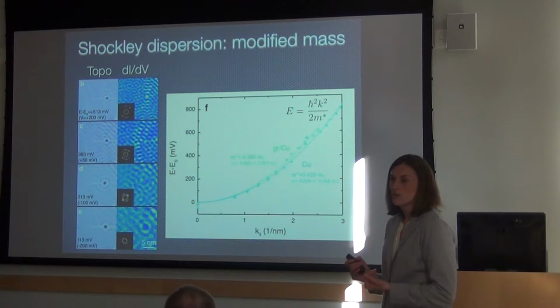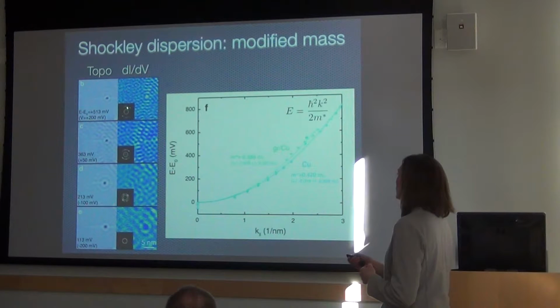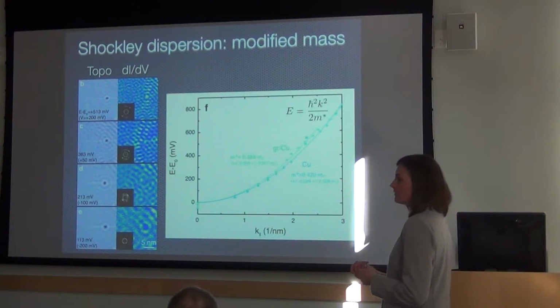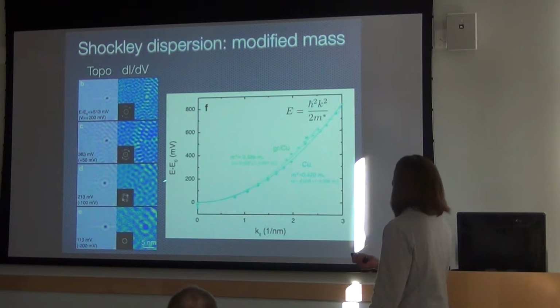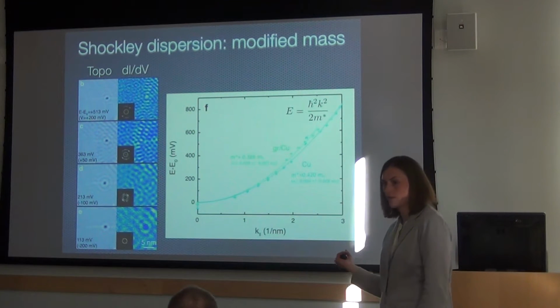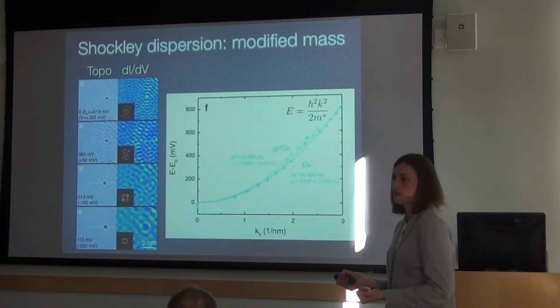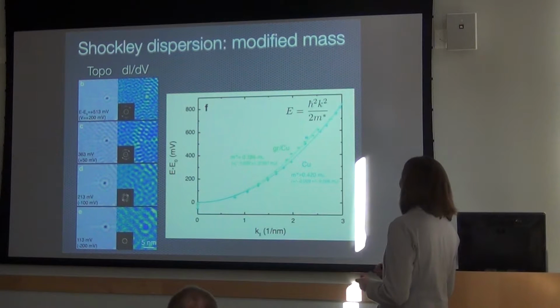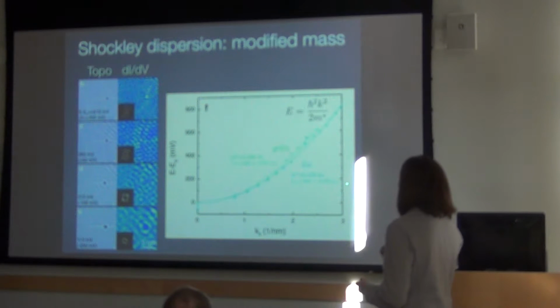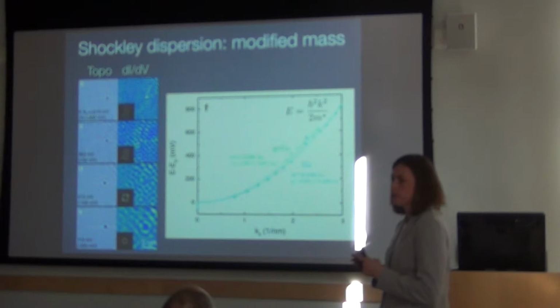We can analyze that and do a Fourier transform, find the momentum of these scattering electron waves, and then plot them as a function of the energy of the tunneling electrons. And we get these very nice parabolic curves showing that these are behaving like free electrons with a modified mass. And the interesting thing that we found was that the effective mass of the electron scattering is significantly different on the graphene-covered copper regions than in the bare copper regions.